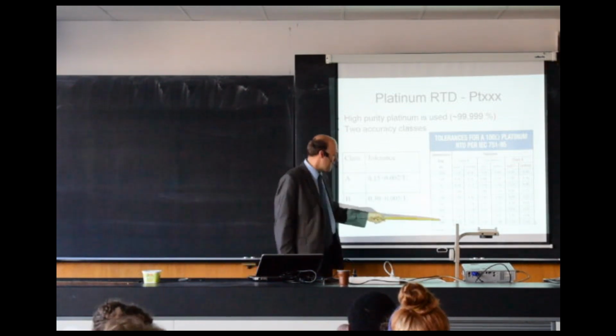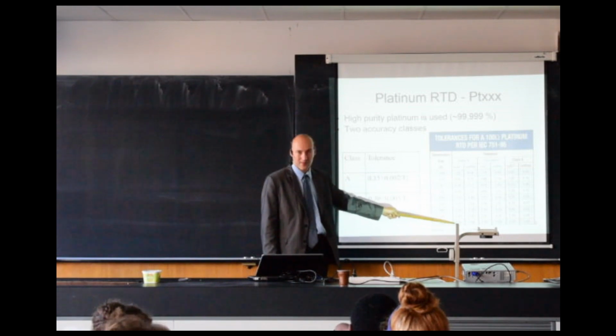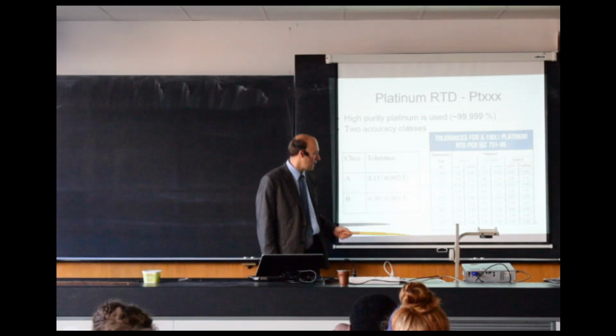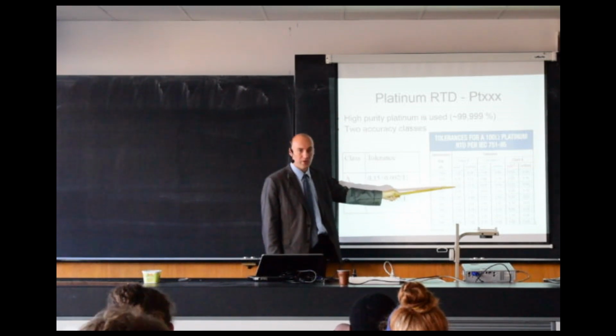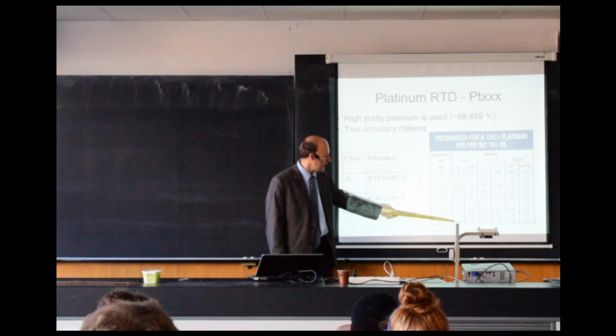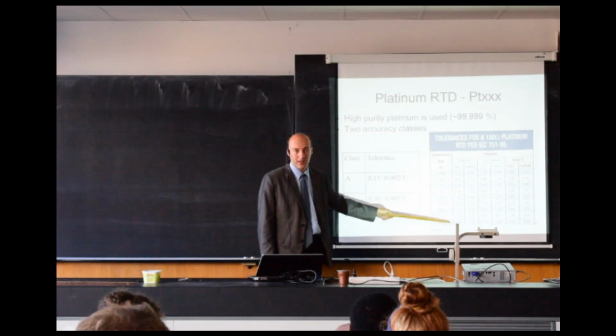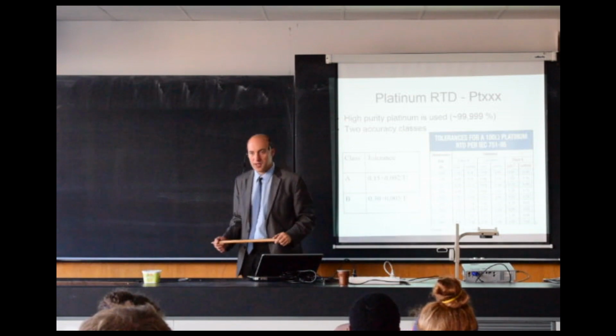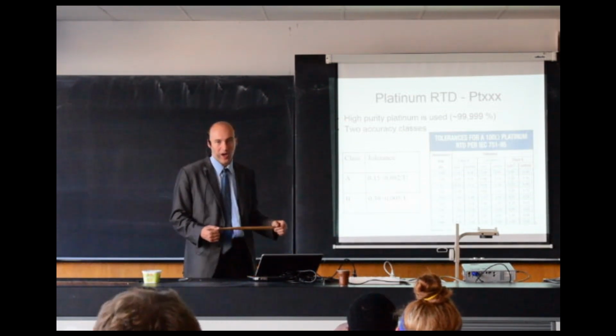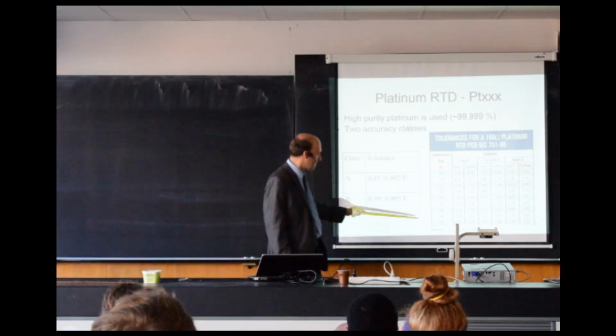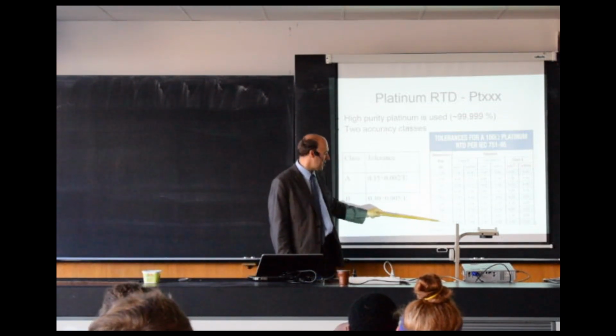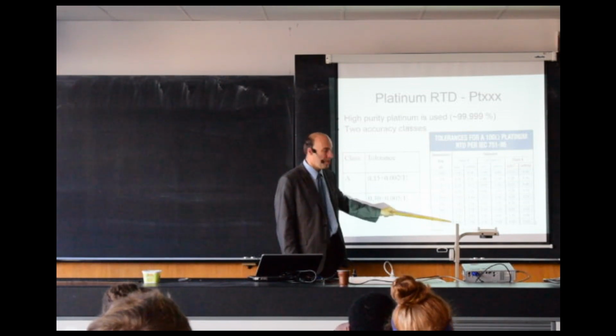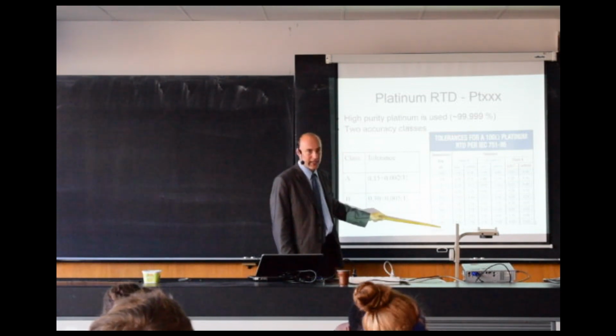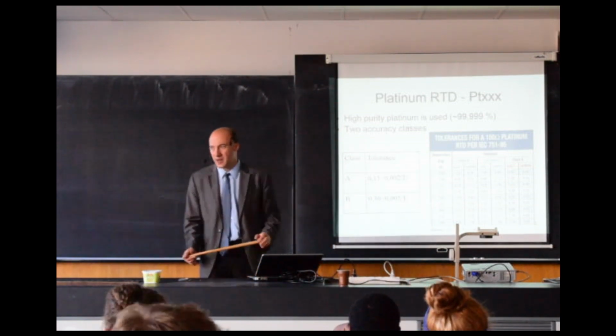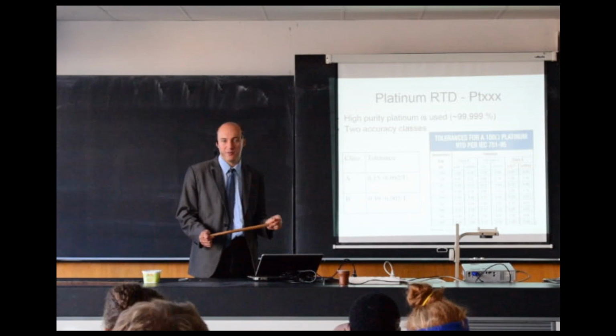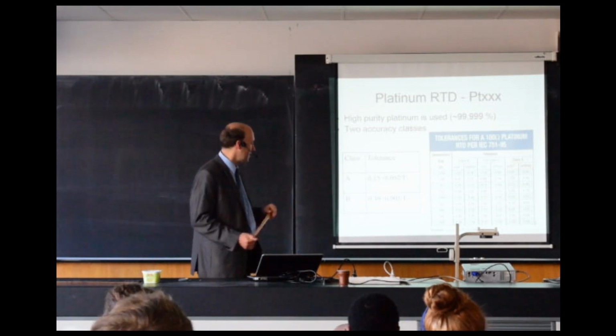The Class B sensor is typically twice as inaccurate as Class A. So for 0, you see 0.3. For 600, this is even worse, 3.3. But still, it is quite accurate. For example, compared to a thermocouple, if you compare 600 and 3.3, this is something like 0.5%. So this is really accurate. For a thermocouple, typically you can expect something like 1, maybe 2%, maybe even bigger. So this is really an accurate sensor.